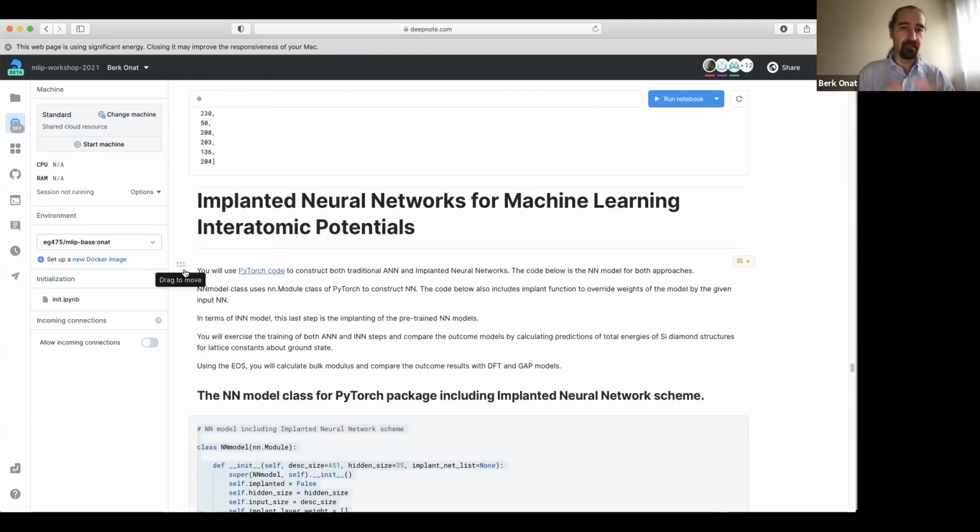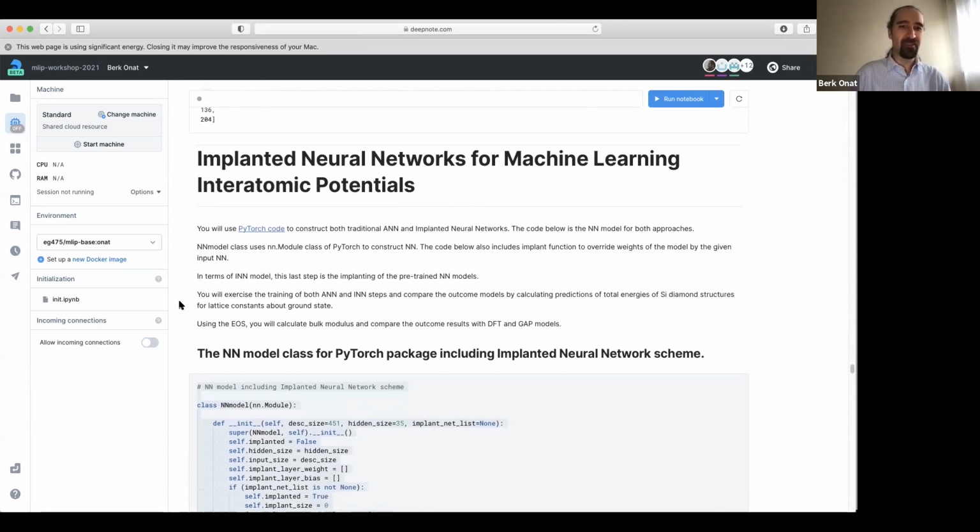We extend our descriptor vector with the SOAP using 9 and 9 for radial and angular part, and then L numbers. But we found that we don't need to use the 450 elements of this descriptor for our data sets. We shrink down to 20, which is really fast for training the neural network.